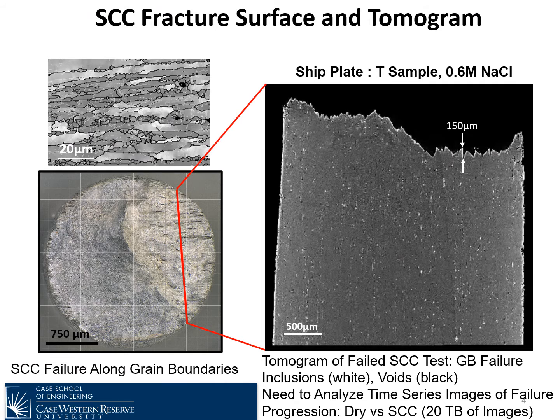If you look at a sample that's broken, first of all in the SEM on the bottom left, you'll see that there are regions on that thumbnail in that sample that look like you have fracture along grain boundaries, and the grain boundaries are shown in the top left. That only happens for so long because eventually catastrophe intervenes, and that's the region in the left-hand portion of the left image. Well, if we take a tomogram of just that broken sample and look at one slice, not a 3D slice, but one slice, we can see evidence of those grain boundary fractures, as you can see that they're labeled. But we also have other information.